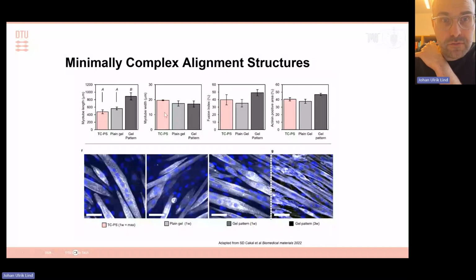And if you then compare these skeletal myoblasts on these patterned gels, what you see is, as compared to regular tissue culture or just unstructured gels, we get better organization, we get longer myotubes, typically up to 1 millimeter in size, so that's approximately 10 times larger than you typically get in conventional bioprinting. And you get a better fusion index, so more of the cells will participate in the myotubes, and over time, you get nicely well-defined sarcomeres resembling native tissue.